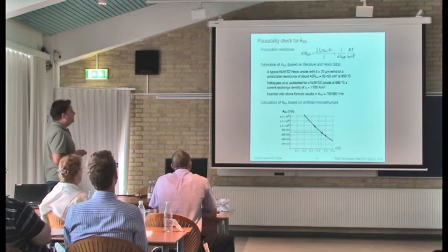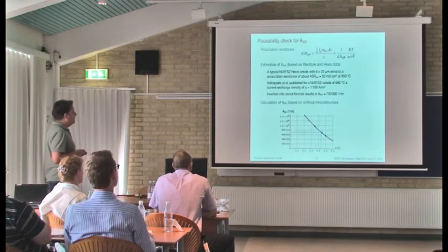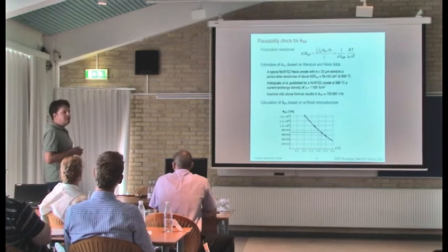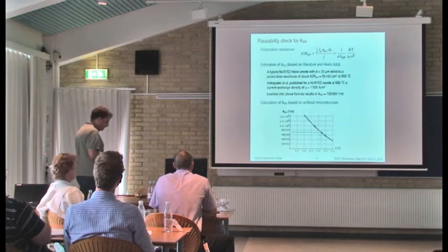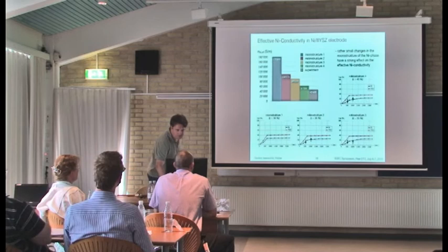And it turns out that it gives a value of this interface area of 700,000 1 over meter, which somehow corresponds well to what we calculate. And it's actually more than surprising, I must say. But it's the first check and needs further investigation.